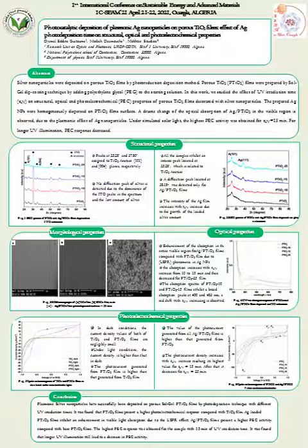Figure 4 presents UV visible absorption spectra of the prepared films. Compared with pure porous TiO2 films, all the silver-loaded films present an enhancement of the absorption in the entire visible region, which is ascribed to the localized surface plasmon resonance, LSPR, of silver nanoparticles.